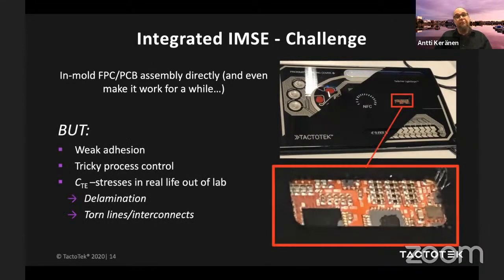Let's zoom inside the control systems in a part which has taken some environmental testing. The molded plastic doesn't adhere well to components, or to the large parts of the FPC. The molding process is tricky to control when you are not allowed to wash out the components needed in the controls. And not only this: you can still handle some of those things, especially the process control, but the process control doesn't help you handling the environmental stress in use. That in practice means